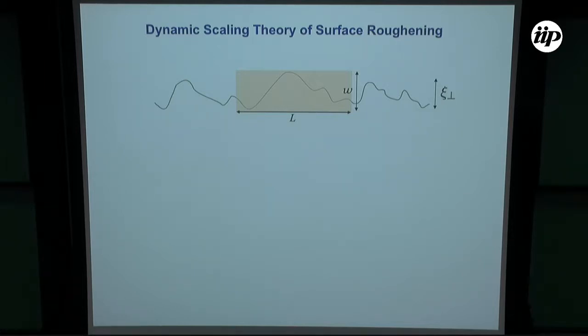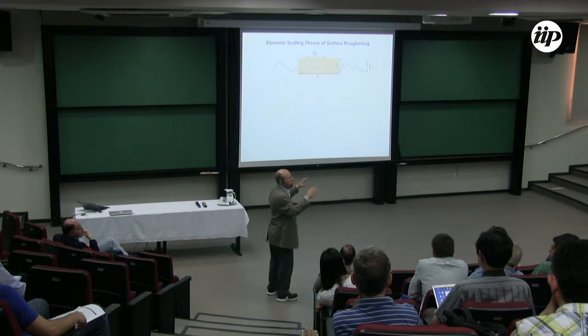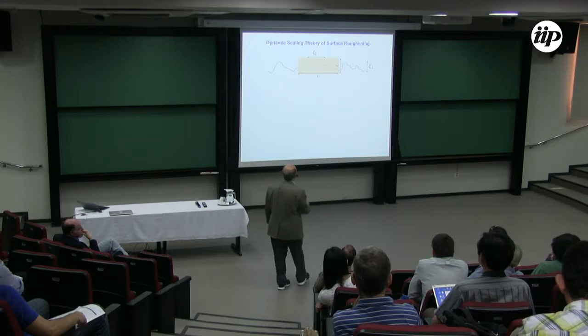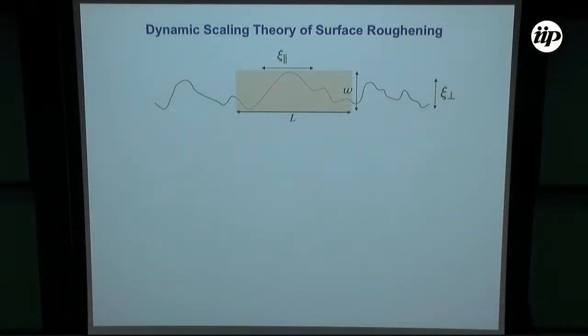In addition, if you concentrate on any feature on the surface, right, as a function of time, it doesn't stay steady. It's not a static problem. It's a dynamic problem. So these features evolve, and what they do is they spread with time. And how they spread can be thought of as the spreading of correlations, just like, you know, the Ising model that David was talking about. There's a correlation length. Here, xi parallel is some kind of correlation length between different parts of the surface along the surface, whereas xi perpendicular gives you correlations perpendicular to the surface. So we have two correlation lengths.